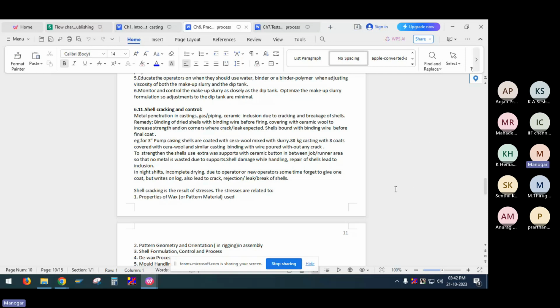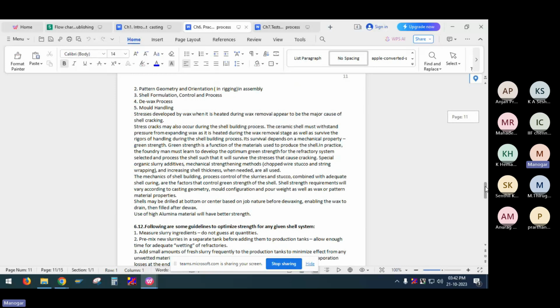Shell cracking is the result of stresses. The stresses are related to properties of wax and geometry of the pattern and orientation in the rigging, that is assembly, shell formulation and process control, the de-waxing process and mold handling. These are the reasons for cracking of shells and related defects, because when the shell cracks internally, nobody can see it, then this broken ceramic will come as inclusion in the casting. Stresses developed during de-waxing are the cause for shell cracking.